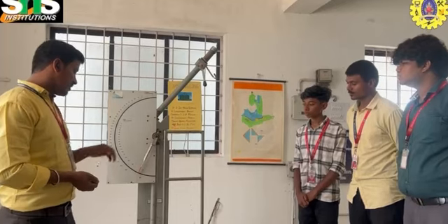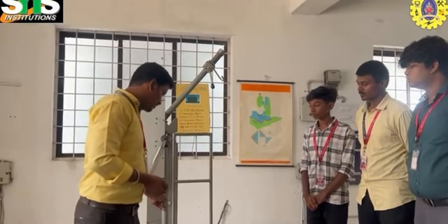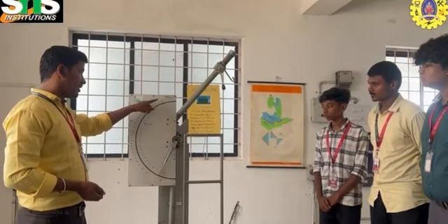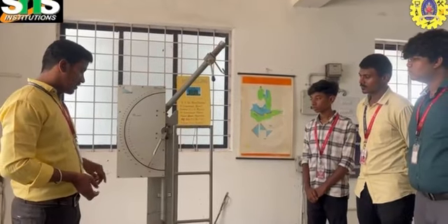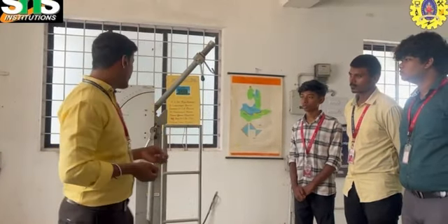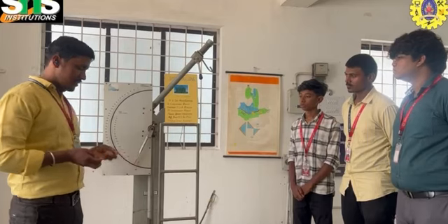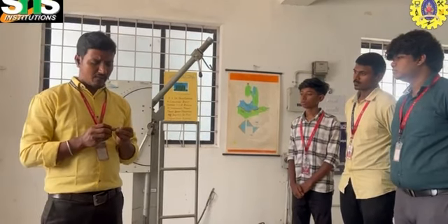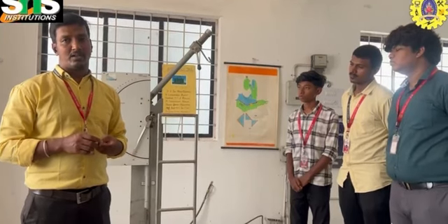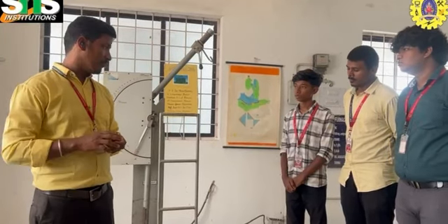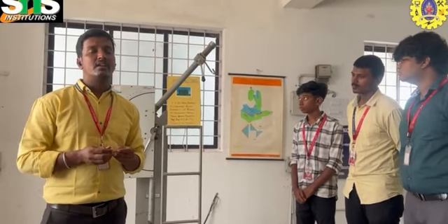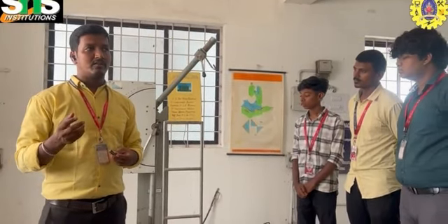Basically, we can say how much energy can be absorbed by the material when a load is applied. In the equipment we have one pendulum and a joule scale. One test is Izod, the other is Charpy. We have our material, mild steel, and we should have a dimension range for every Izod and Charpy specimen. For Izod, we have a 75 mm long specimen with a 10 by 10 mm cross-section. For Charpy, we have a 55 mm long specimen, and the width and thickness are 10 by 10 mm.